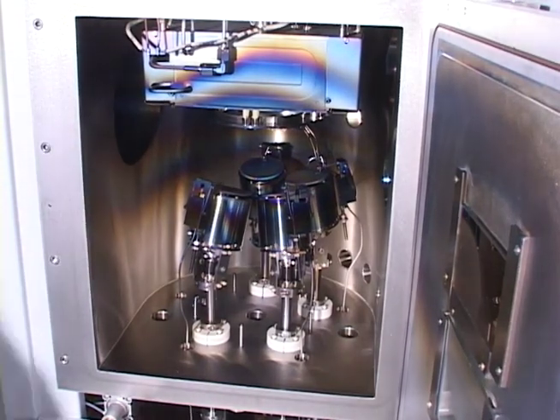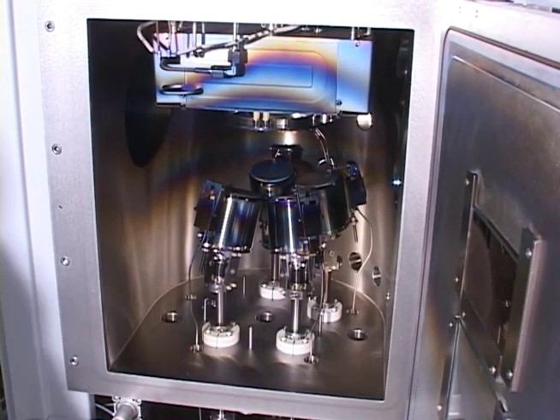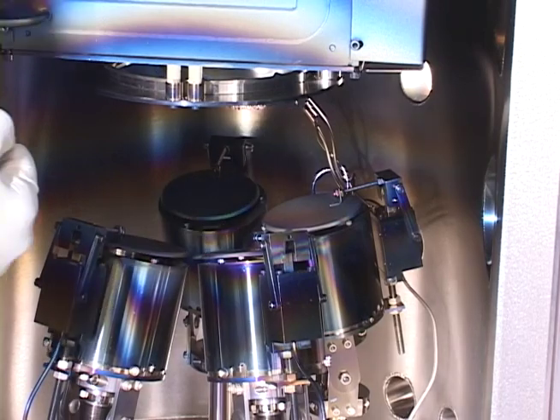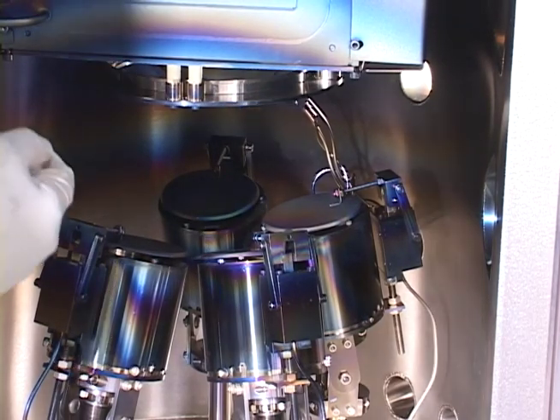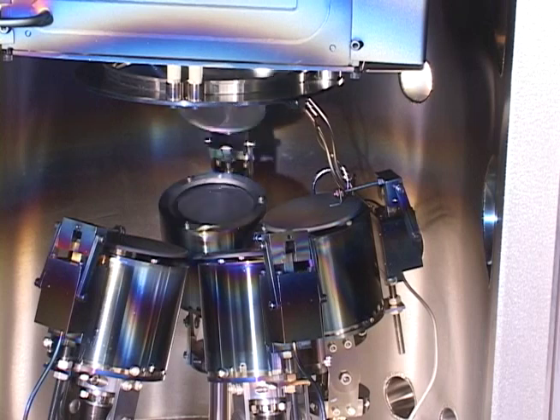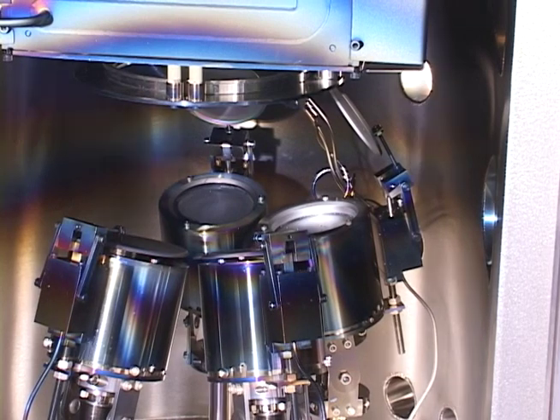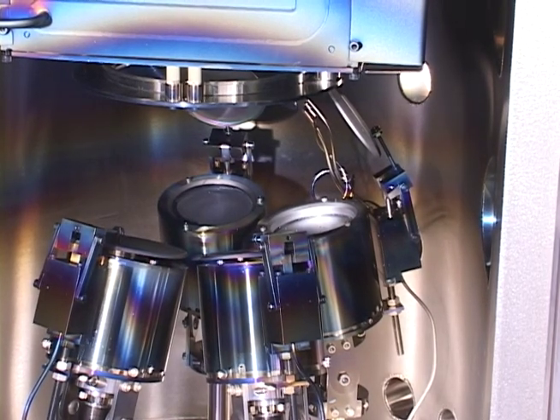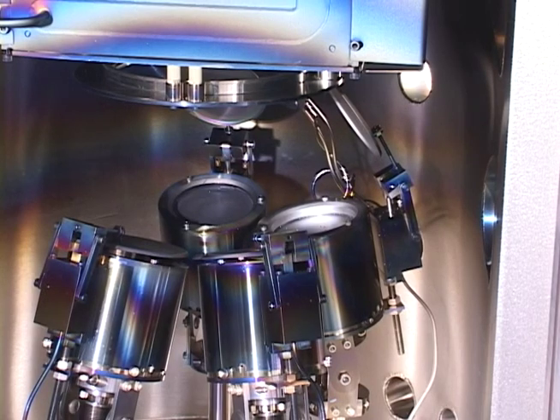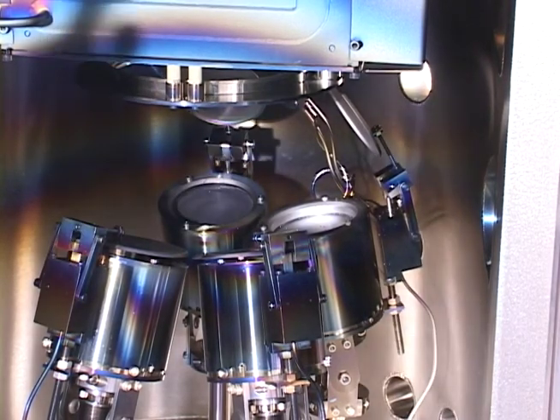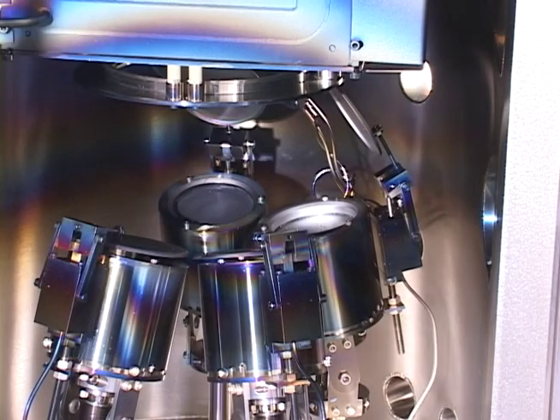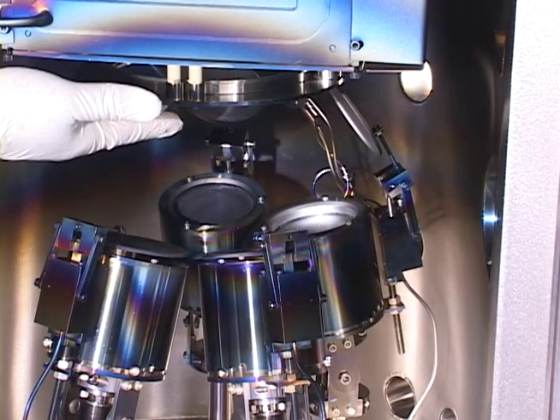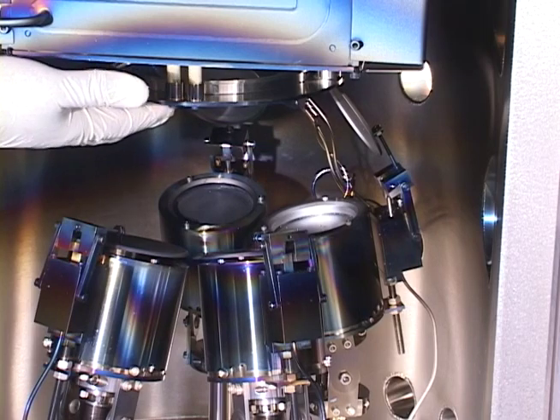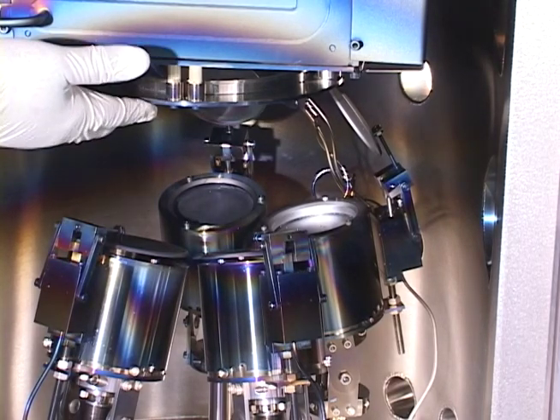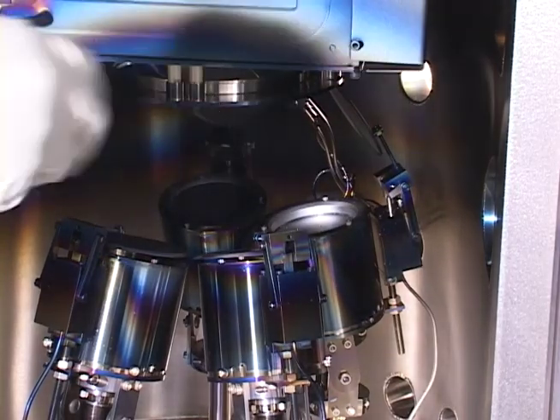And inside the deposition chamber, you see that you have several target guns, and they have lids on top of them. And again, this is how the target will look. This is target number 3, as I'm pointing to, is ITO, indium tin oxide. And say, for instance, we want to deposit ITO onto a substrate. The substrate will be located directly above the target guns and is being mounted onto a sample holder. Of course, the door will be closed.